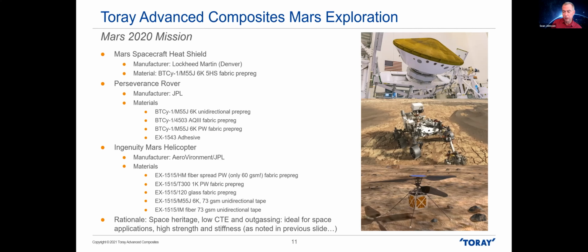These materials are also extremely good for dielectric performance. So if you have reflector surfaces or areas where, conversely, you need high dielectric transmissivity and very low loss, we put those with things like Astroquartz, which are used for terrestrial radomes, high performance radomes, and they find equally good application in space. I'd mentioned some of the complementary products earlier. In this case, there's a cyanate ester adhesive that's very well tuned to work with the BTCY1. That is its complement. And then, of course, the star of the show, the Ingenuity Mars helicopter.